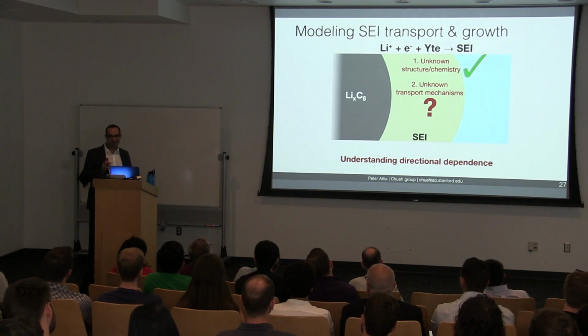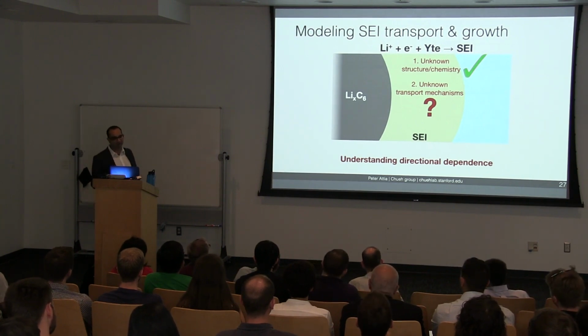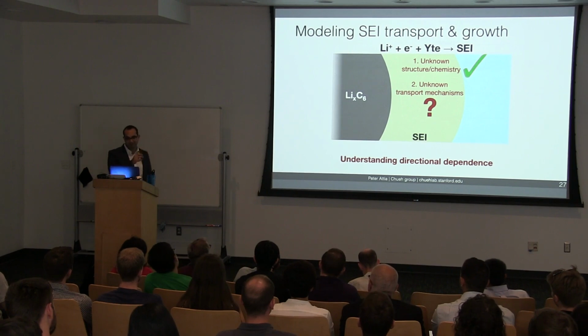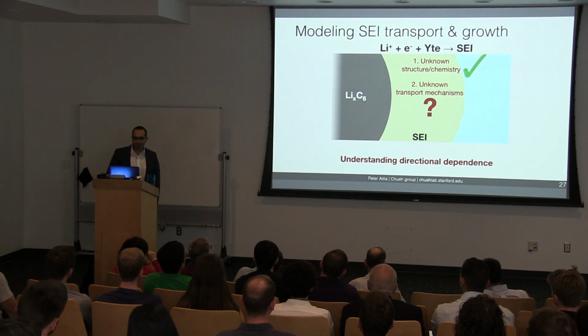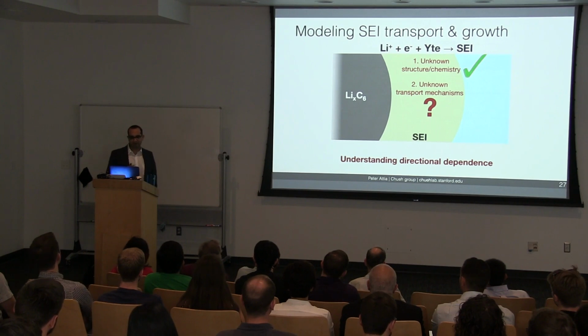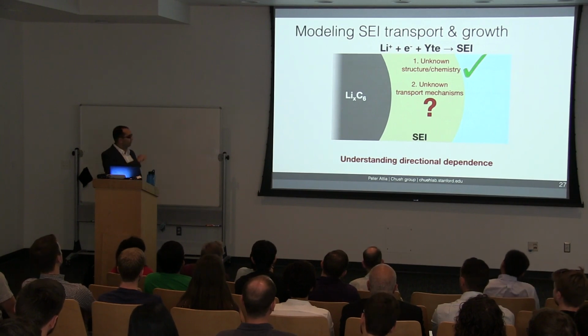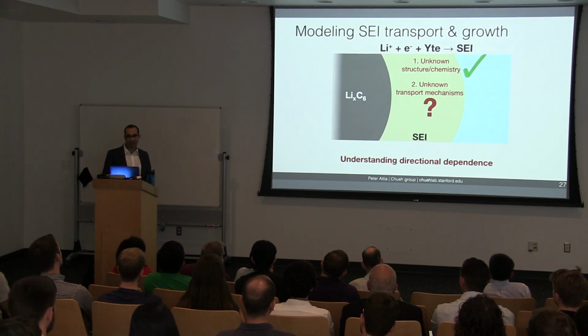So we quantified the SEI growth kinetics and found this very strange observation that SEI grows a lot during lithiation, but appears to be turned off during delithiation. In a way, the kinetics of SEI growth appear to act as a diode. They only work in one direction. So to better understand this, we built a model that can try to explain these results, and in particular, the strange observation of the SEI growth and direction dependence.